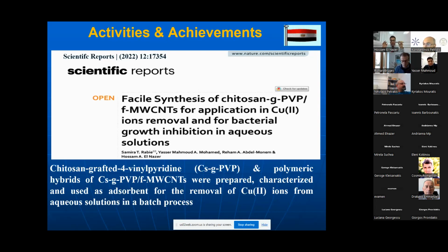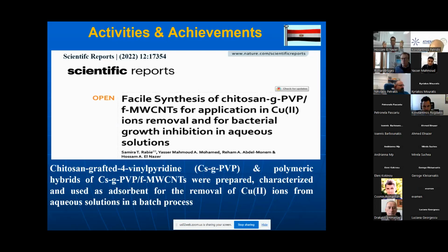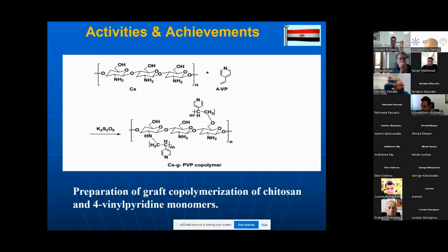And we have also in this paper succeeded in the synthesis and preparation of highly efficient hybrids from carbon nanotubes and chitosan. Also we have good findings and results using this composite. We have more than 90% removal of copper ion, and we see that this is a mechanism of